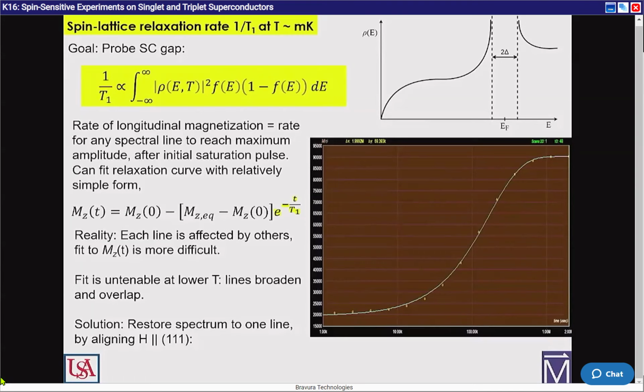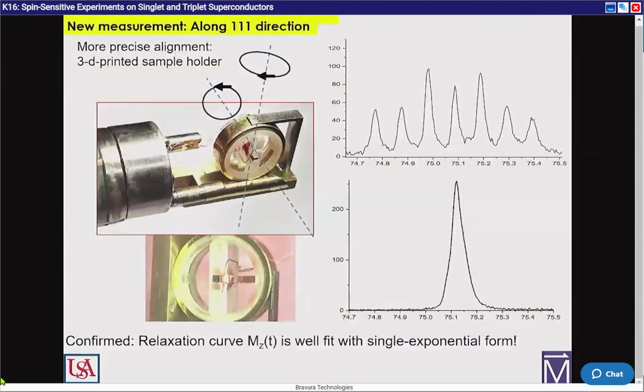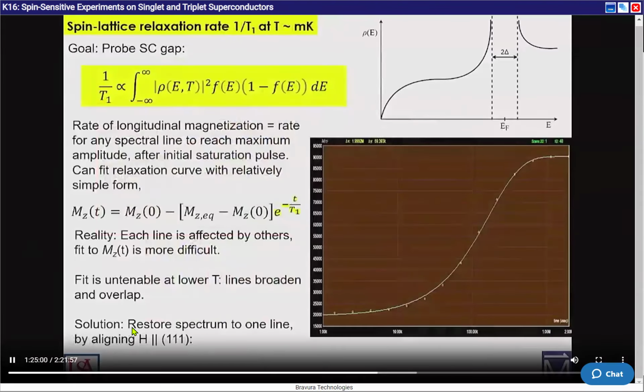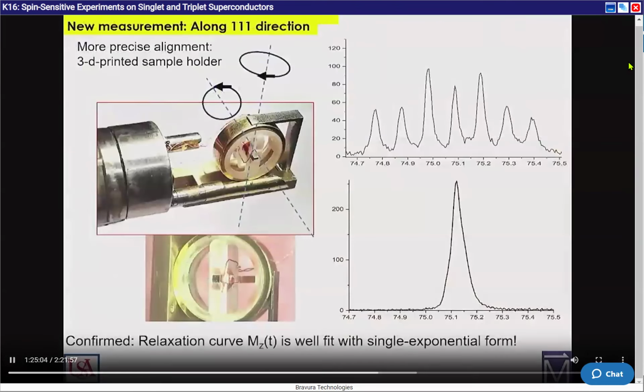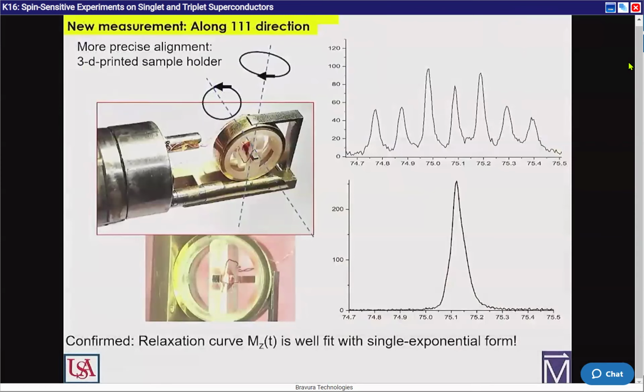And we do that thanks to a lovely 3D printed, custom-made sample holder. There's a sample in there, together with the two-axis goniometer. And there you go. There's the collapse. We have one line. And you guessed it, when we saturated that puppy, we got that. So we get a nice, reliable measurement of T1 even at low temperatures.